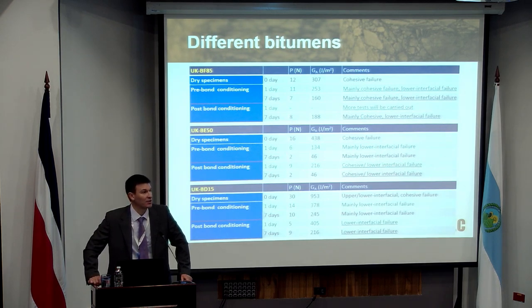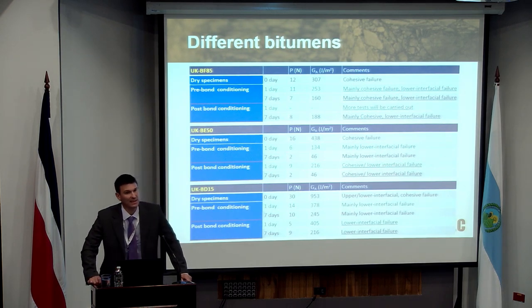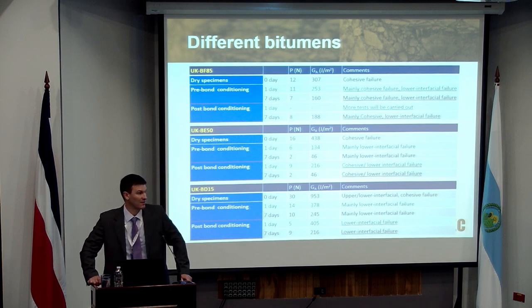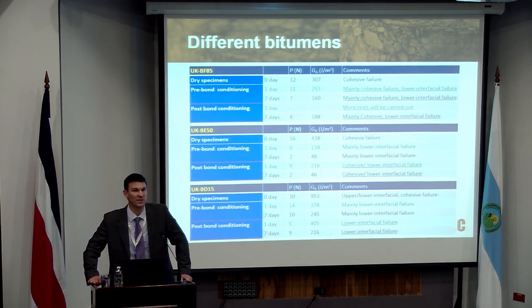That just summarizes the results for bitumens. We know already that the bitumen is not the dominant factor. We know that behavior tends to be dominated, in terms of moisture damage, by the type of aggregate that we're using. But this just illustrates that if we had exactly the same type of aggregate and we played around with the bitumen, we do see subtle differences. The softer binders will tend to perform slightly differently to the harder binders. But in general, we're seeing roughly the same: 2 or 3 days of moisture conditioning gives you about a 50% reduction in your fracture strength in terms of the peel test.